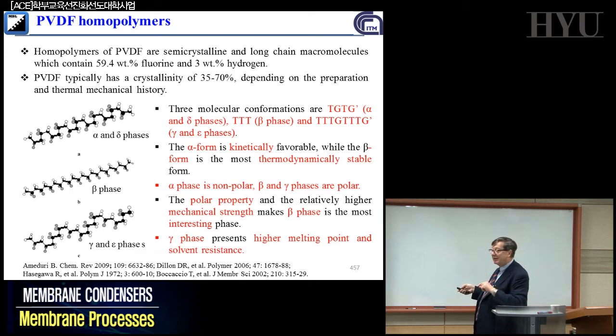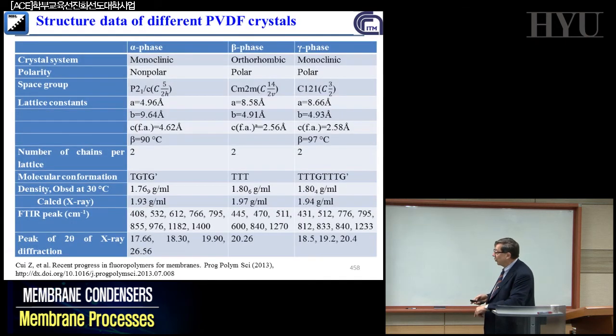there's another interesting part. The alpha form is kinetically more favorable, but is not thermodynamic. The thermodynamic form is the beta, which means that if you are trying to predict on the long term the aging of your membrane, if you want to have a membrane that will stay for 5 years, 7 years, running the same way, if they are not stable from a thermodynamic point of view, these membranes probably will have aging phenomena with time that you can eventually predict, and if you know what is going on, it will not be a surprise. But if it's alpha, as it is not beta, the problem can be different. So it is very important to understand which kind of form is present in your system. And until now, as you know, these things were not really very well addressed.